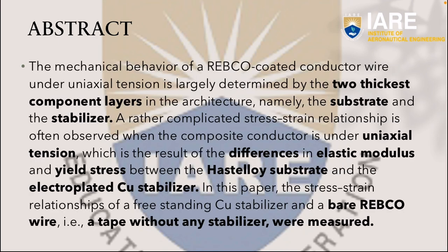Abstract of this presentation. The mechanical behavior of REBCO coated conductor wire under uniaxial tension is largely determined by the two thickest component layers in the architecture, namely the substrate and the stabilizer. A rather complicated stress-strain relationship is often observed when the composite conductor is under uniaxial tension, which is the result of the difference in elastic modulus and yield stress between the Hastelloy substrate and the electroplated Cu stabilizer.